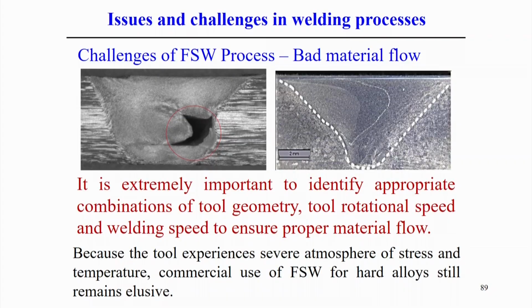But the issue or challenge in this process is mainly insufficient material flow. If we look at this figure, it is a welded joint, but we can observe a small gap. This happens when the material flow is not good, and it can create this kind of problem. The right-hand side is a good weld joint, joining these two components in the solid state welding process.